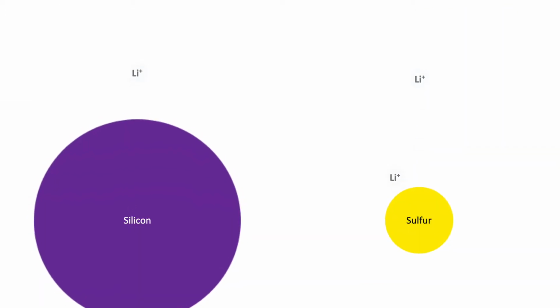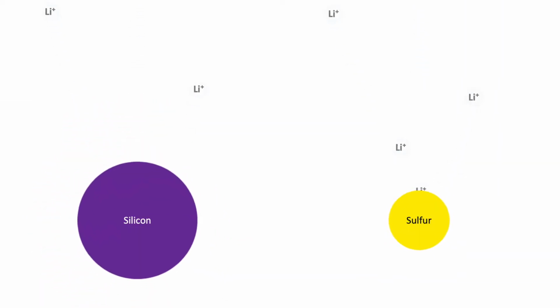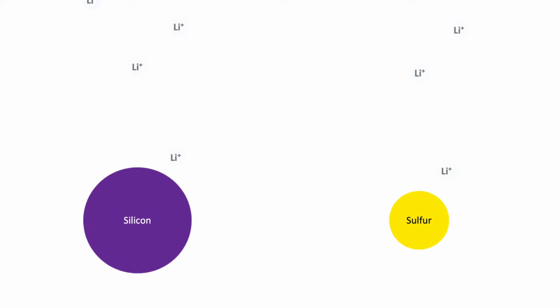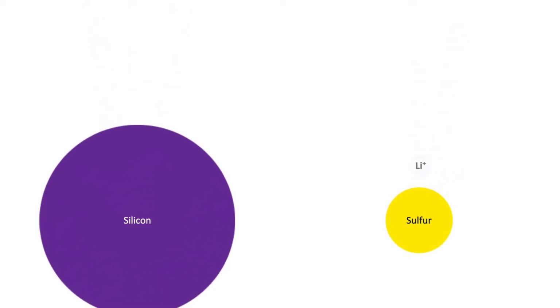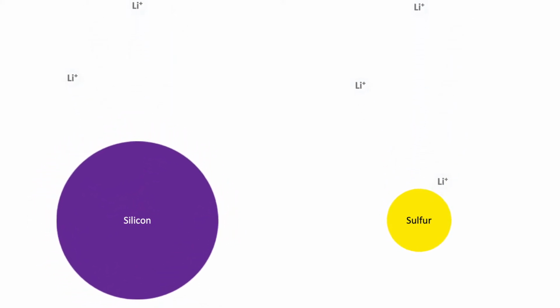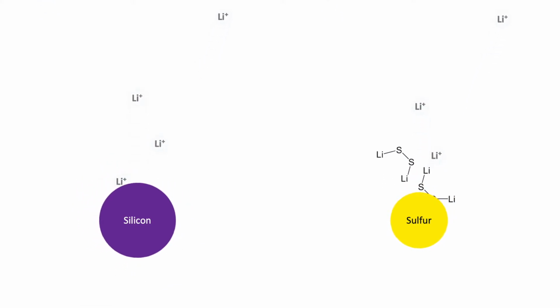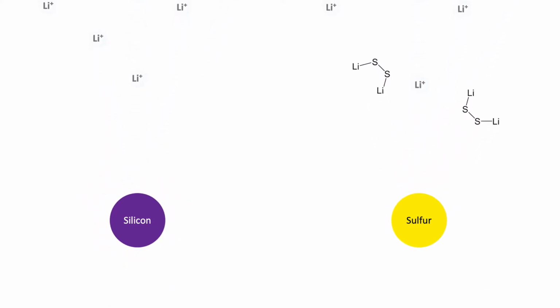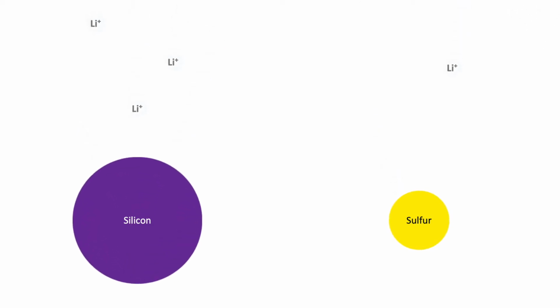With silicon, the capacity drops so quickly because every time the battery is charged and discharged, silicon particles can expand and shrink by over 400%, causing the electrode to fall apart. With sulfur, the capacity drops so quickly because when lithium leaves the electrode, atoms of sulfur like to tag along for the ride, and those lithium ions remain bonded to that sulfur forever and can't be reused.